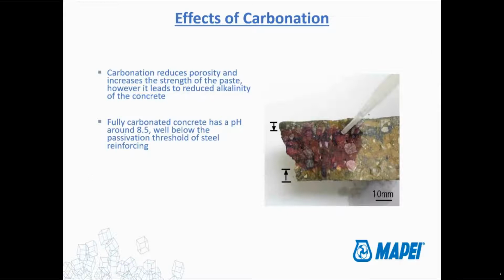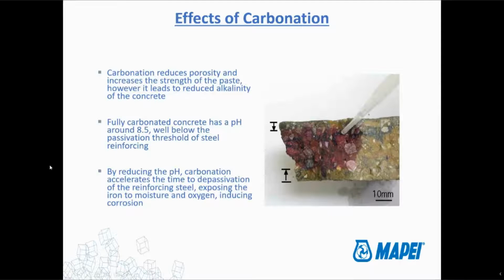So fully carbonated concrete, what we mean by fully carbonated concrete is essentially concrete where the carbonation has penetrated as far down as it's going to happen. It gets to some distance down into the concrete, and then it stops happening. So in the picture that you see here, what they did was just put some phenolphthalein solution on the concrete. You can see it reacts in the middle portion of that sample. So in that middle area where it's red, you don't have any carbonation happening. But at the surfaces where it's exposed to the air, that's where the carbonation has started to happen. So you get that lower pH. So you don't get the reaction of the phenolphthalein with that bright red color where it's a lower pH concrete. But again, by reducing that pH, carbonation is just accelerating the time to depassivation of the steel, which will expose it to being able to start reacting with the chloride.